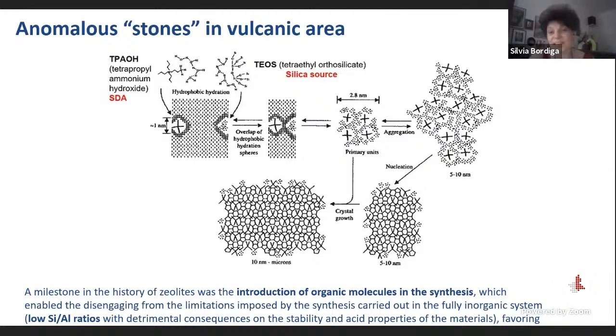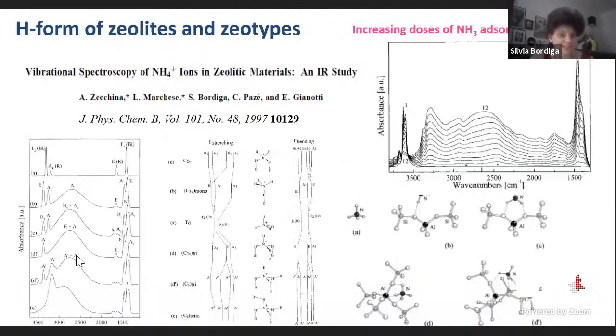The peculiarity of these materials is having at the beginning, after the synthesis, a hybrid structure, because we have the organic inside the channels and the inorganic part, which is making the lattice. Upon calcination in air, we can remove completely the organic part and reach in the end the porosity of the material. And this is a big point in favor of these materials, for which we can easily obtain porosity in the lattice. And I will show that in case of MOFs, this is not always the case.